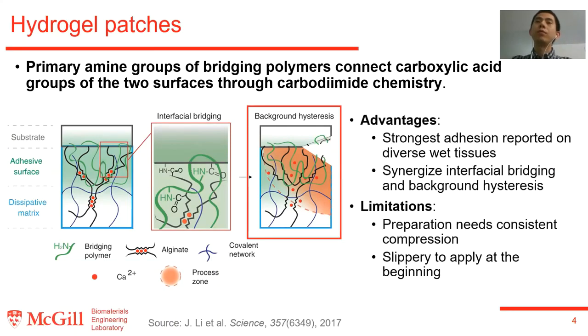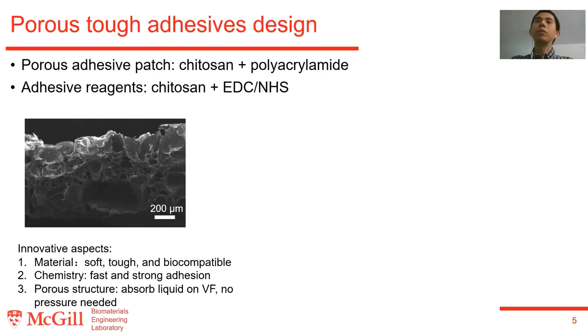This strategy can provide a strong and tough adhesion between hydrogels and tissues, but it requires the hydrogel to fully contact the wound, so applying pressure is needed to squeeze out the interfacial fluids, and also it takes about 5 minutes before the hydrogel can adhere to the tissues. In this project, we propose a porous tough hydrogel adhesive design to minimize the needed pressure during use and to accelerate the adhesion formation.